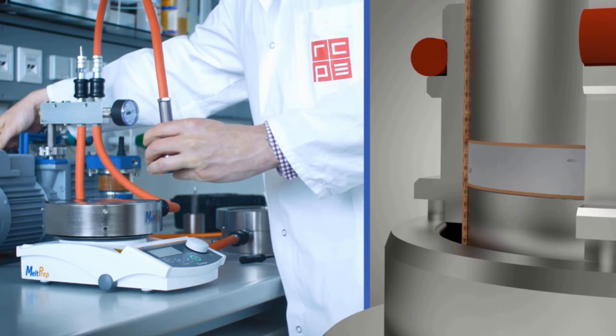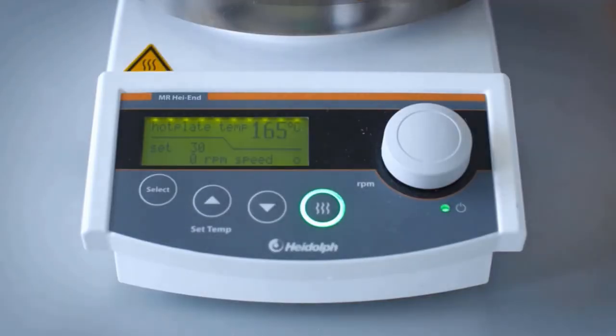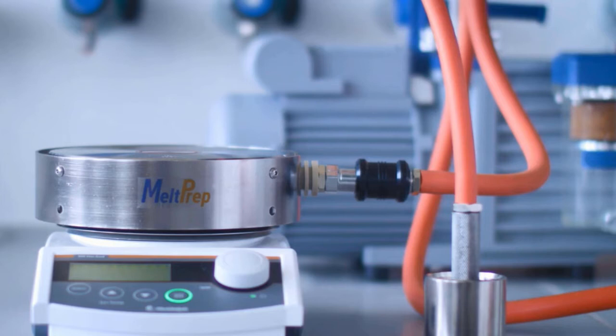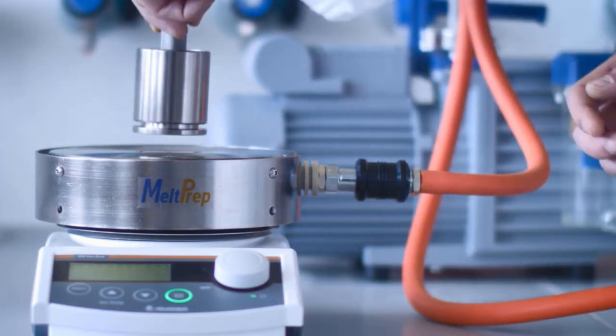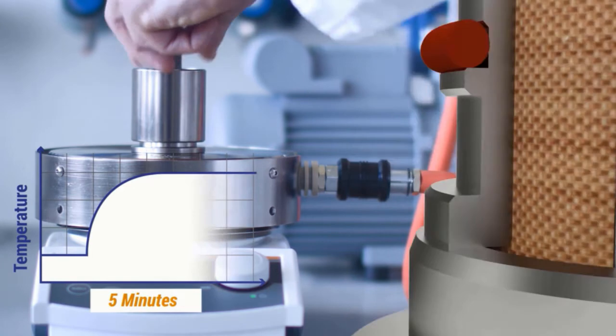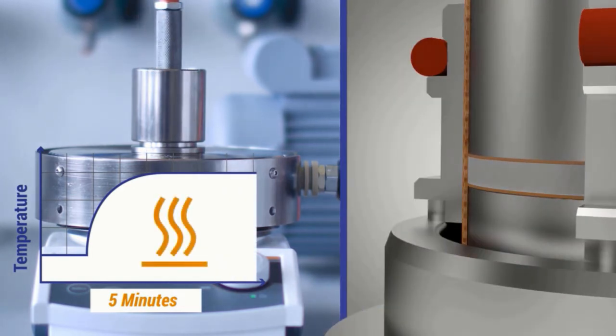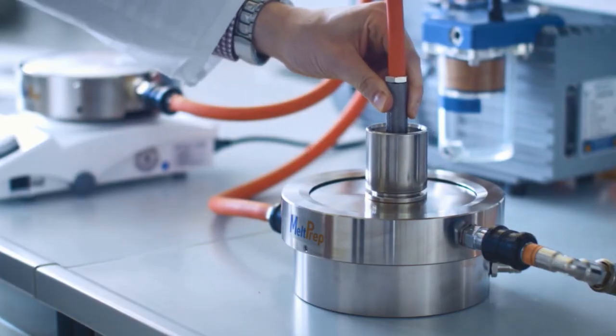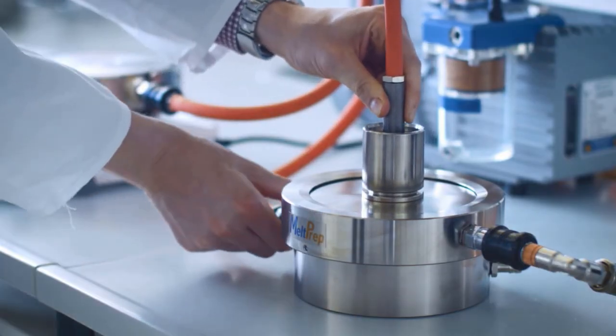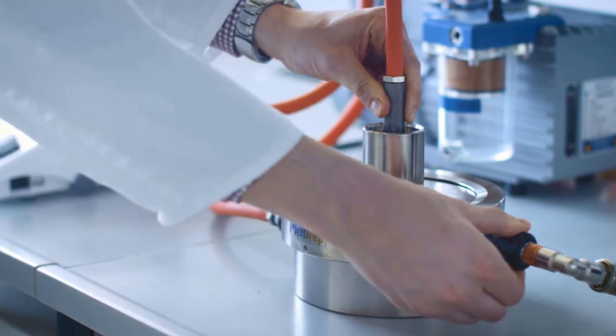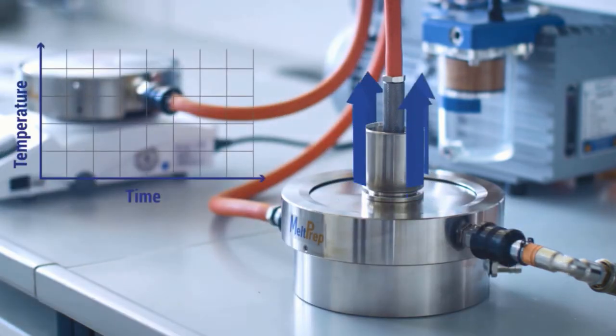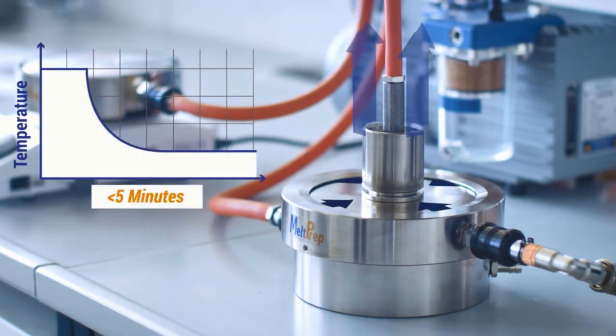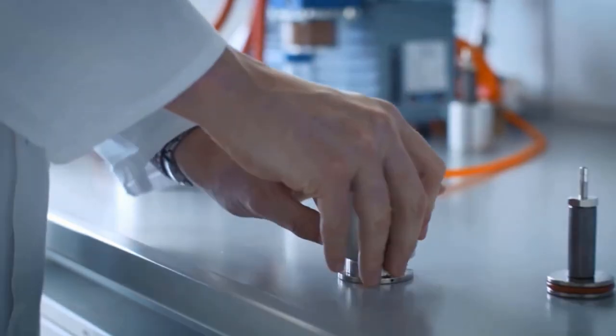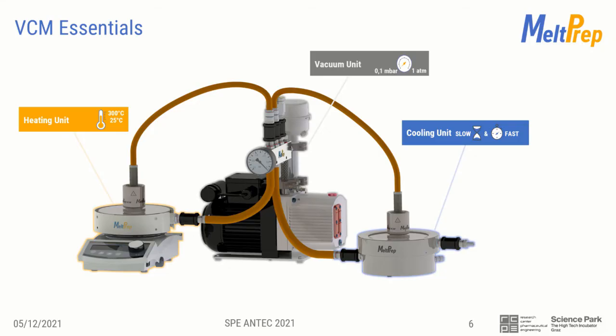After the VCM tool is connected to the vacuum unit, the air is drawn out and the powder is compacted. Subsequently, the VCM tool is placed on the hot plate to initiate the melting. The powdery material forms a homogeneous melt. As a rule of thumb, this takes about 5 minutes. Once completed, the VCM tool is transferred to the cooling unit to cool it down to ambient conditions. After cooling, it is taken apart and the sample can be released with ease. The PTFE foils can be peeled off like stickers.